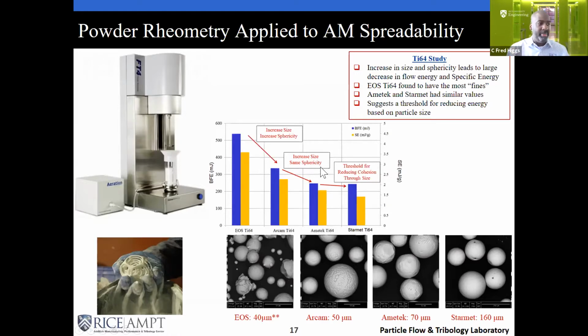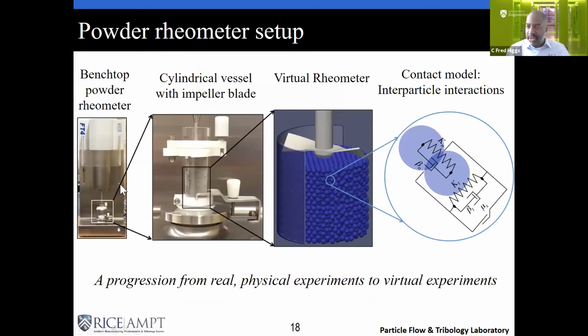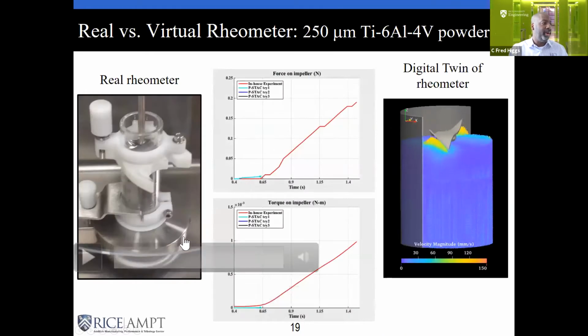So all from this powder rheometer, we can find out things about the powder. And that's going to be important for our modeling, because here you have the physical rheometer. And again, as you get into industry 4.0, some people call it cyber physical, mixing the digital and the physical communities. You'll see how we do that in our laboratory here. So you have a physical rheometer there, which is a cylindrical vessel with the impeller blade going in the powder. We create a virtual form of that rheometer, or a digital twin of that rheometer, and then we do the contact modeling of the particles there, where we use the discrete element method to look at the interactions between the particles there.